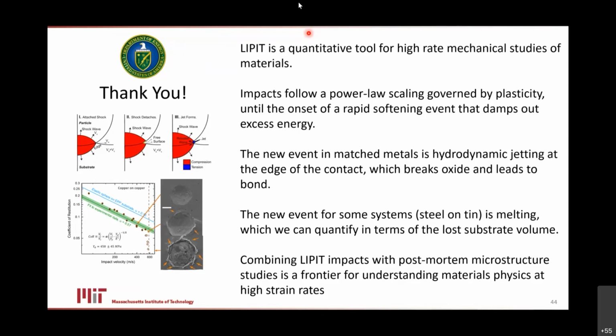So that's an aside. And then there is this bigger question of those hardness values. There are no fitting parameters for those hardness values, right? There's no fitting at all. That doesn't rely on the Wu model. So I can regard that as one measurement of strength. So I have a hardness. Then I can do a bunch of shots and use the Wu model, and I get a second independent measurement of hardness or of strength. And how those two connect, that is still a mystery. In the world of hardness testing, we call the ratio of yield strength to hardness the constraint factor. No one, to my knowledge, has explored the constraint factor at these very high rates. So you're definitely asking a smart question and you're poking at a really open area that I hope to address in the coming year or two.